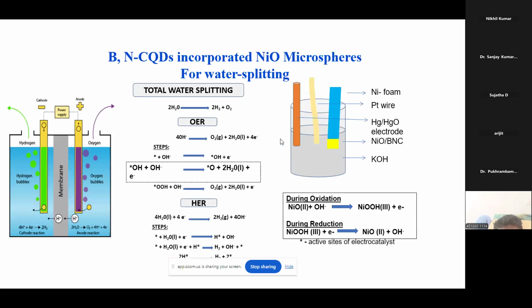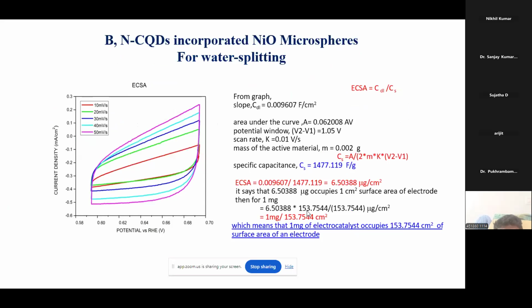Then this is the same system with water splitting applications and total water splitting. It gives this OER application, and HER also is giving good performance. During oxidation, nickel oxide reacts with OH minus, and it provides nickel oxyhydroxide. Then during reduction, nickel oxyhydroxide with the electron becomes nickel oxide. So total water splitting takes place. Then ECSA we calculated with surface area.